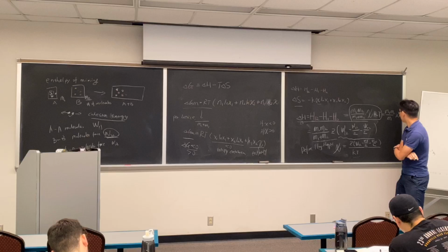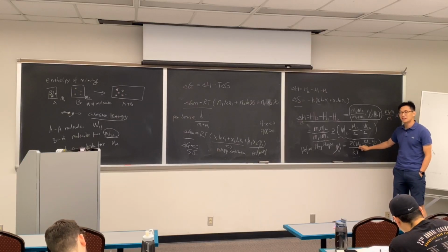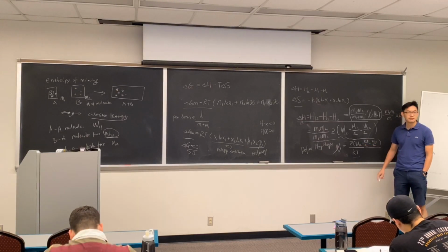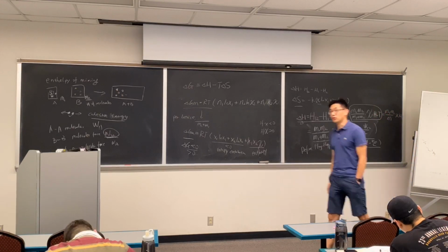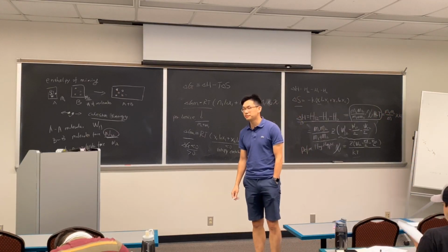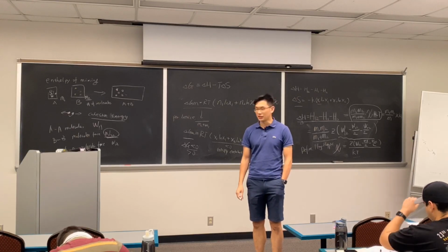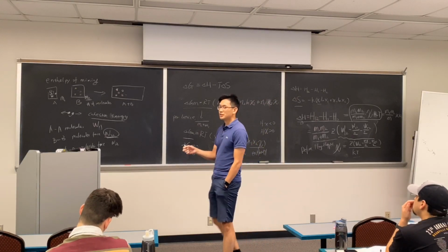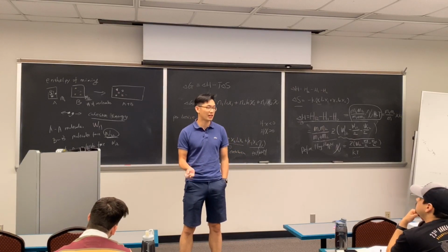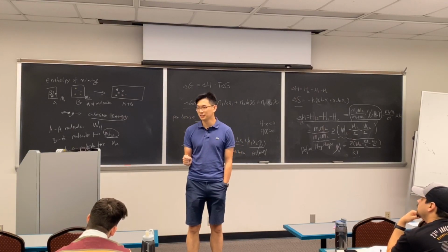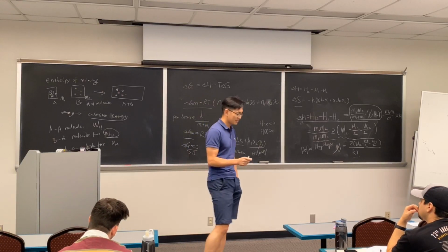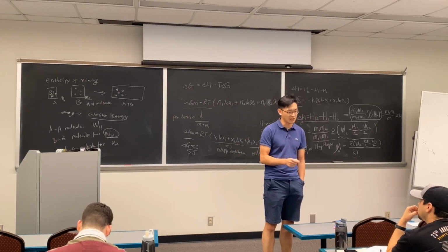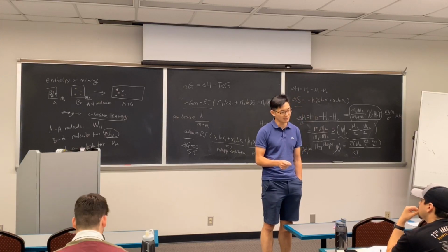Again, coming back to this topic, chi large means there's a lot of unfavorable interaction in here. How does it compare? You can actually look up chi parameters for different components and get the chi value. For example, PMMA and polystyrene has a relatively low chi value. They're more likely to mix. While PDMS and polystyrene has a very large chi value. They are very unlikely to mix.